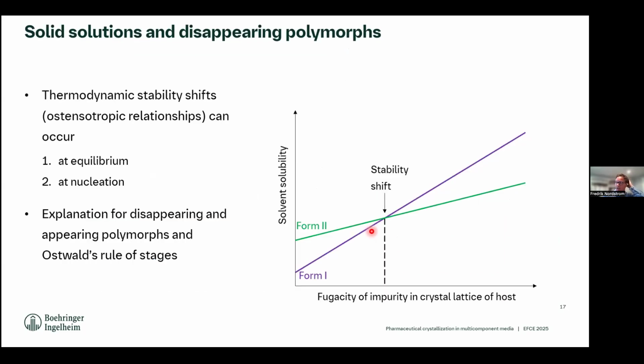Okay, and just a quick word here on disappearing polymorphs, because if you see here in the early stages of crystallization, you're creating a very high level of impurities in the solid phase, so higher solubility, and that can actually lead to how different polymorphs can form, and so they can appear and they can also disappear. So if I'm adding in or taking away an impurity, I can tweak the direction of which polymorph becomes thermodynamically more stable. And there are two ways this can actually happen. In the first case, you can have what we call again the enantiotropic relationship. So you have a convergence in thermodynamic stability with the increasing concentration of impurity in the crystal. And you would then crystallize it here, and suddenly the metastable form, when it's pure, becomes the thermodynamically stable form, right?